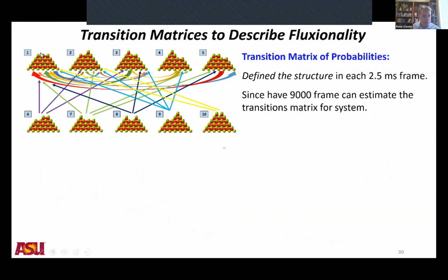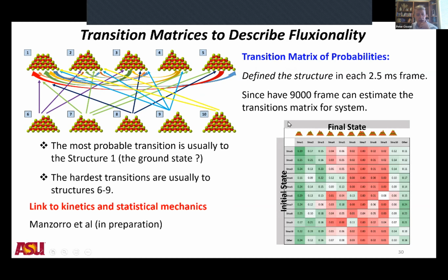So here's a cartoon representation. If I'm in state 1, what's the probability of the next state being state 2 or 3 or 4 or 5? And so you can see there are all these possible transitions. And if you have enough data, you can start to define transition matrix probabilities. And here's, I'll just finish with this. Here's an example of one of these transition matrices that Ramon has defined, where each matrix element is the transition probability between one metastable state and the other.